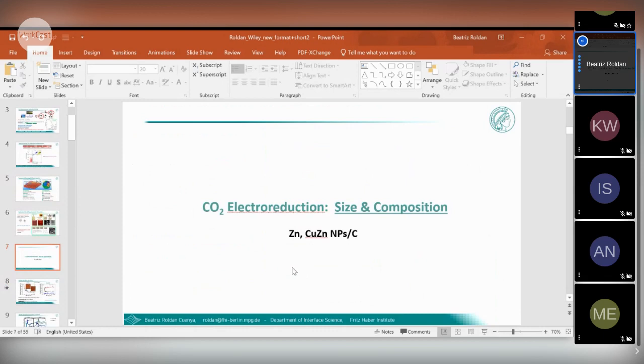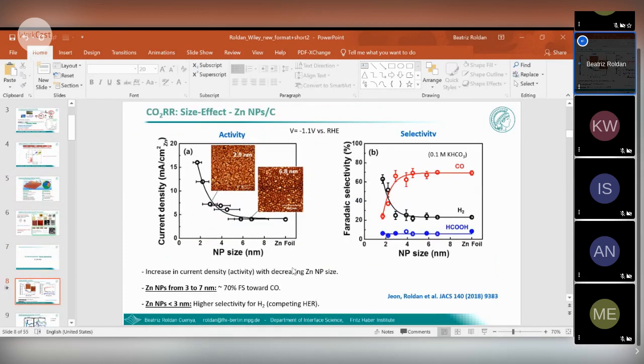I'm going to give you an example with zinc nanoparticles. Zinc is a metal that is able to produce carbon monoxide. And you can see here that with decreasing particle size, we can see an increase in the current density. This means an increase in the activity. So this is promising. We can have a high activity for the high surface area material, in this case, the smallest zinc nanoparticles. The problem is the selectivity.